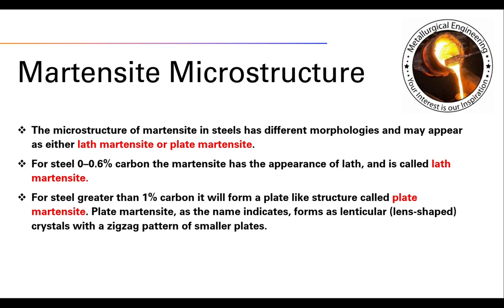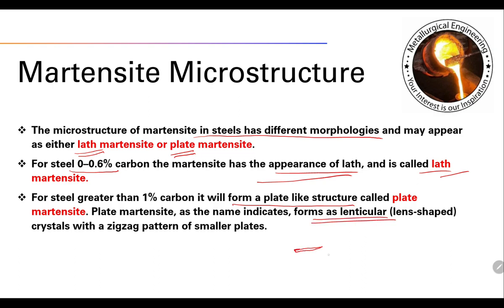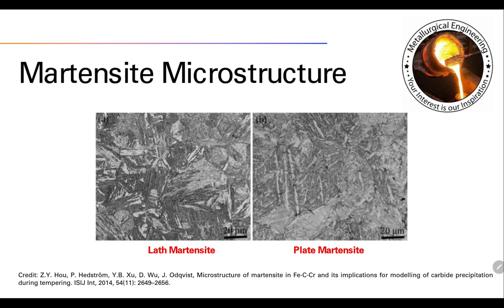There are two kinds of microstructure in martensite: lath and plate. For steels with 0 to 0.6% carbon, the martensite has a lath appearance, called lath martensite. For steels with greater than 1% carbon, it forms a plate-like structure called plate martensite, which forms as a lenticular shape with a zigzag pattern of smaller plates. The microstructure images shown correspond to these two morphologies.